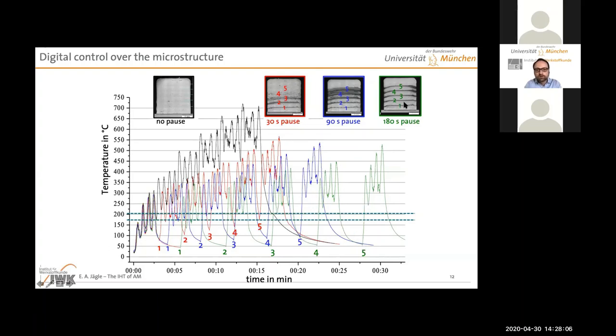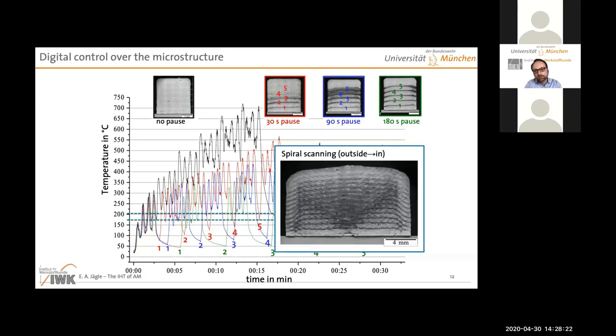So you have these very homogeneous layers every time. And then 90 seconds is perhaps the sweet spot for more homogeneous hardness. So by writing your machine code, your G code, you have direct access to hardness or no hardness in your material. And that's of course very nice.